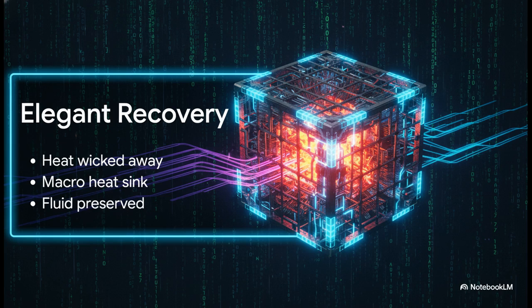Let's quickly summarize this beautifully elegant recovery sequence. First, the graphene instantly wicks the localized heat away from the hydroclusters. Second, the entire aluminum block steps up, acting as a massive heat sink that eagerly absorbs all that thermal energy. Third, because the heat is sucked away so incredibly fast, the molecular integrity of the PEG carrier liquid is completely preserved. No boiling, no vaporizing. And finally, because it survived the heat spike, the core simply relaxes back into its compliant, flexible, phase-I Newtonian state just mere milliseconds after the impact. It cools itself instantly and is perfectly ready for the very next strike.